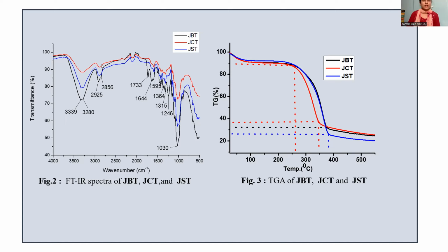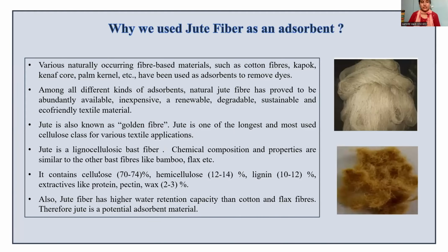So you can see there is a difference between these three FTIRs. In the JBT, there is a very good band at 2925, and the sharpness of the band decreases as we move from JBT to JCT. The peak at 1733 is totally removed, and 1644 is also removed. These are the major peaks getting removed when we convert JBT to JCT. What we are doing is removing the lignin from the jute fiber. Jute fiber contains cellulose 70 to 74%, hemicellulose 12 to 14%, and lignin 10 to 12%. Lignin gets removed when we treat it with caustic, and somewhat hemicellulose is also removed.